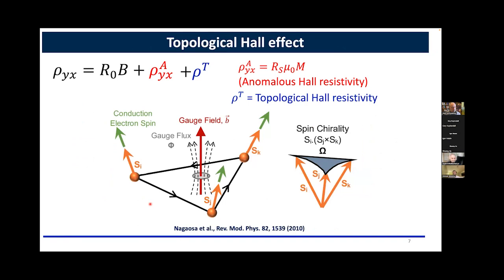We know that for a topological Hall effect, we need a scalar spin chirality. And if we look at this magnetic state, this transverse conical spiral state, where the topological Hall effect appears, this phase is present at lower temperature also. This phase extends all the way up to room temperature. But only at a certain interval of temperature do we see the topological Hall effect. The transverse conical spiral itself cannot generate the topological Hall effect because it doesn't have this scalar spin chirality.